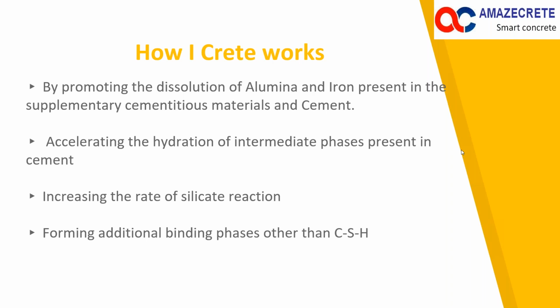Here, the point is this: it promotes dissolution of alumina and iron present in the supplementary cementitious materials and cement. So we know that alumina and iron components are present in cement and cementitious systems, and iCrete works on these materials, and then it accelerates the hydration of intermediate phases and increases the rate of silicate reaction. Most importantly, it forms additional binding phases other than calcium silicate hydrate gel, which is normally formed in any cement hydration process. That is how it works on a different level, and that is why we call this a totally different technology.